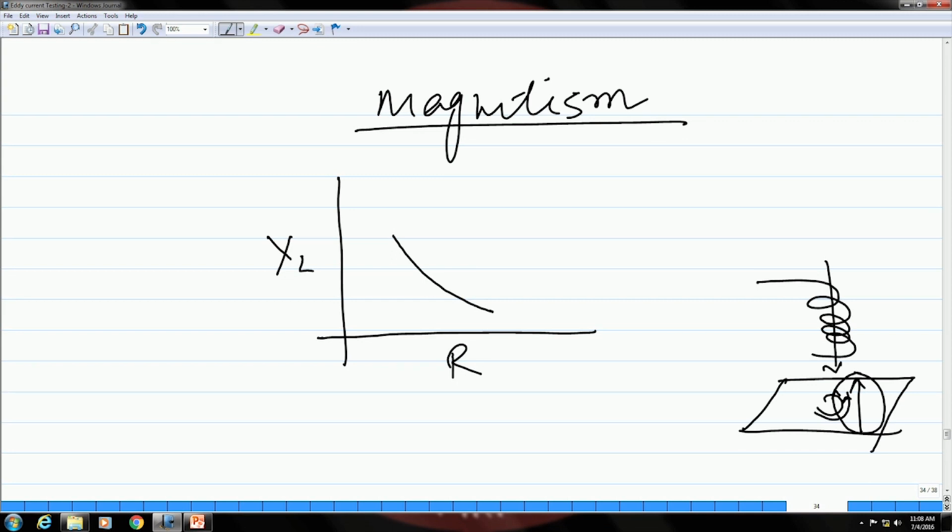It will also reinforce or concentrate the magnetic field of the primary coil. As a result, the reactance will increase instead of decreasing, unlike the non-magnetic material case wherein the reactance decreases. So, this is the effect of the magnetic permeability of the material.